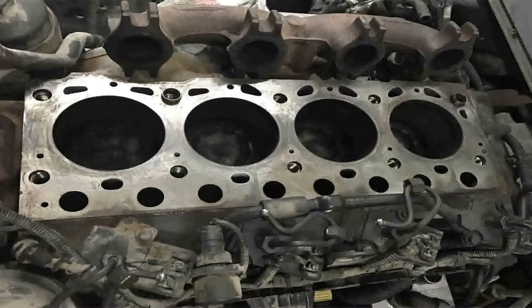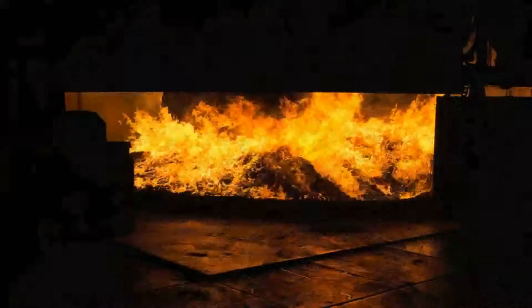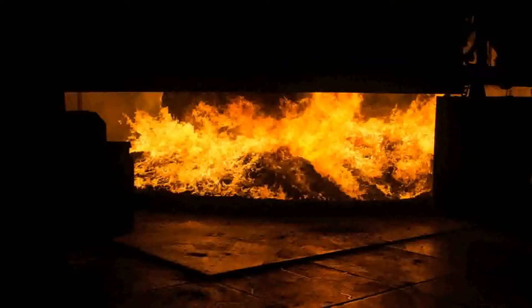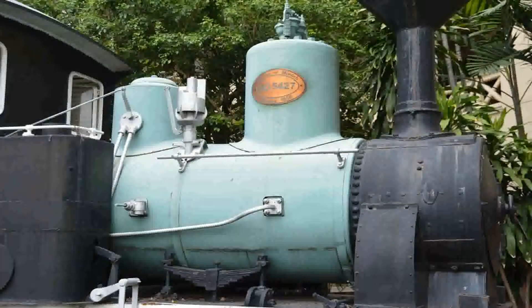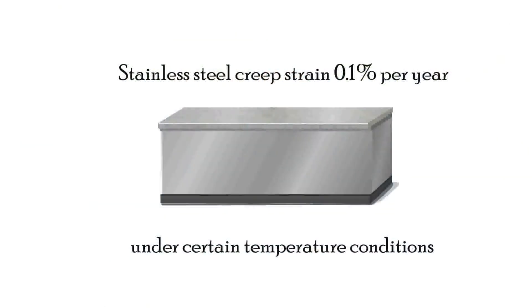At higher temperatures, the creep strain in engine cylinders, furnaces, and boilers should be considered. Creep strain is suggested for stainless steel as 0.1% per year for certain temperature conditions.